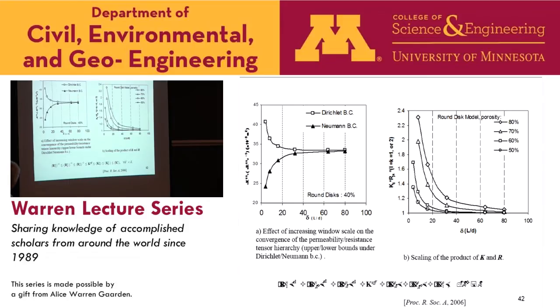Here I'm collecting results for various material systems, actually using this scaling function idea, namely looking at the scalar product of K with R, which if the medium is homogeneous, should be 1. But if the medium is not homogeneous, it will be greater than 1. So here's the scaling function again. Basically, the denser the system, the quicker the approach to Darcy law. This is consistent with intuition.